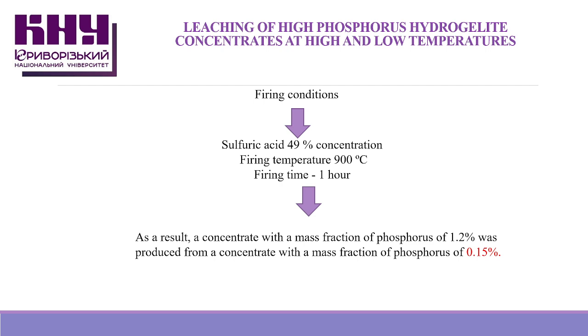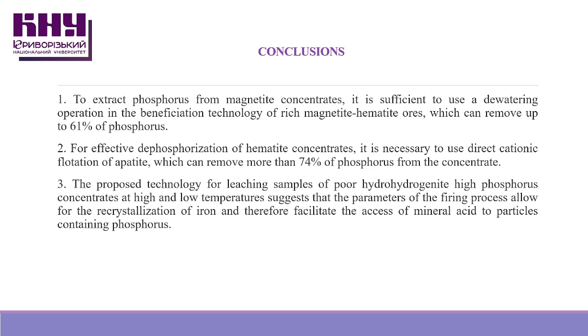Firing was conducted at a temperature of 900 degrees Celsius for 1 hour. Leaching was performed with sulfuric acid at a concentration of 49% for 1 hour. As a result, a concentrate with a mass fraction of phosphorus of 0.15% was obtained from a concentrate with a mass fraction of phosphorus of 1.2%. Based on the results of the work, the following recommendations were developed.